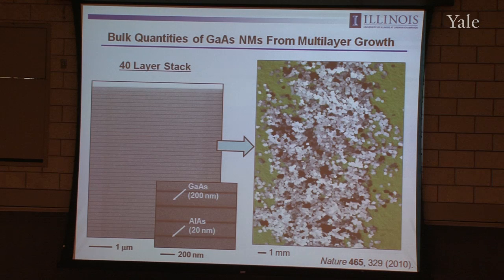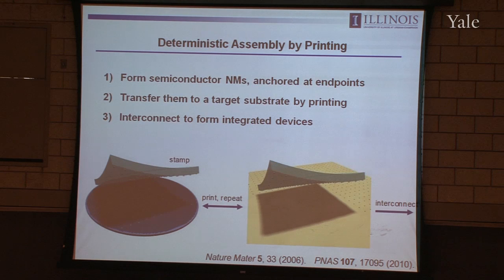The problem is to achieve the kind of engineering yields you need for doing realistic things is extremely challenging. So in parallel with those kind of efforts, we've taken a slightly different tack, which is that if you're creating this material from a wafer-based source in the first place, if you can design the system so that you undercut etch these nanomembranes from their underlying host substrate, but design lithographic structures so that they remain tethered to the underlying substrate in their lithographically defined location, then you can think of that processed wafer as an inking pad in a printing process that uses a soft stamp to pop off of the surface of those wafers selected collections of those nanomembranes, thereby inking them up onto the surface of the stamp, index the stamp over, this is all happening at room temperature and open air,